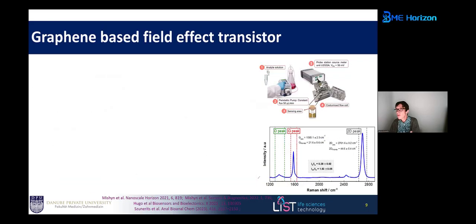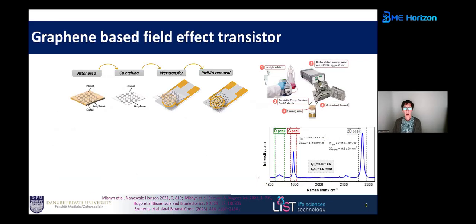But before this, how do we physically construct these types of sensors? Currently, what you have to do is transfer CVD graphene onto the interfaces. The way we do it, we buy, or for the moment we even make, laser-induced graphene interdigitated electrodes, and you put your graphene on it, and you can then use the drain and source current of these interdigitated electrodes as part of your transistor. The devices are all commercially available. You can buy the cell from Micrux. If you do this type of approach, the gate will be a simple silver wire electrode.